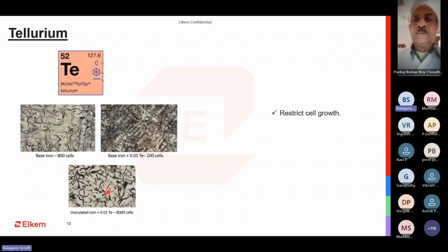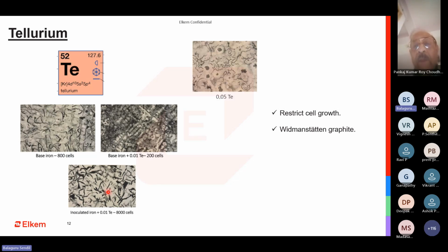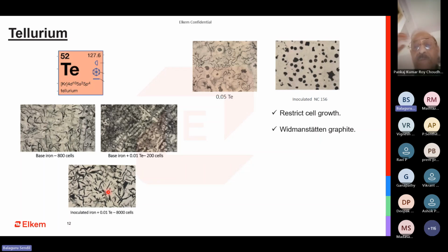So what it does, it again restricts the cell growth. It forms this spiky kind of graphite when starting, which is going to have a drastic effect on your mechanical properties, especially your tensile strength. So if you are going to have samples drawn directly from your casting, then it's going to be a problem. Then for ductile iron, again, it causes the same thing. The conditions are the same.